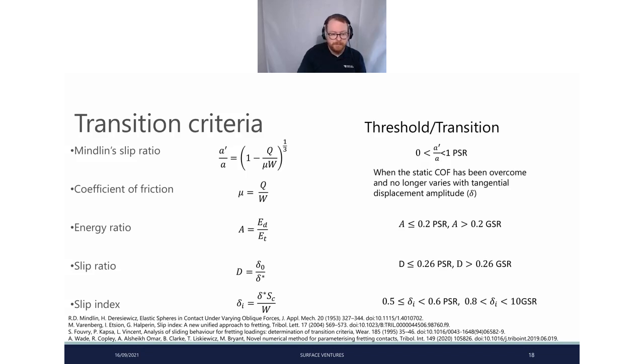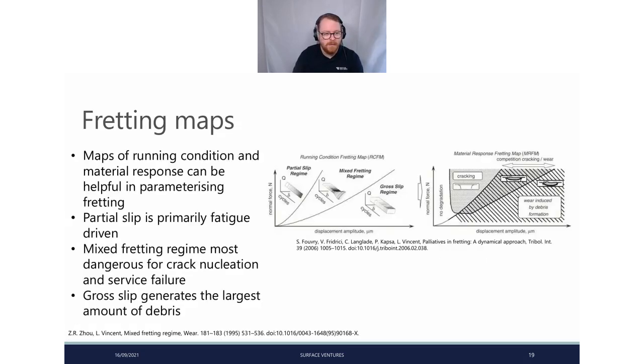Slip ratio, used by Fouvry: 0.26, lower than that is partial slip, higher than 0.26 is gross slip, and then we have slip index as well. Each of these papers will tell you all of the parameters for this, but without extending too long and without making this just talking about maths, that's what there is. I would recommend that you do a little bit of further reading.